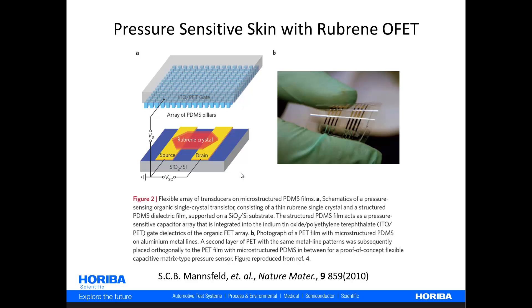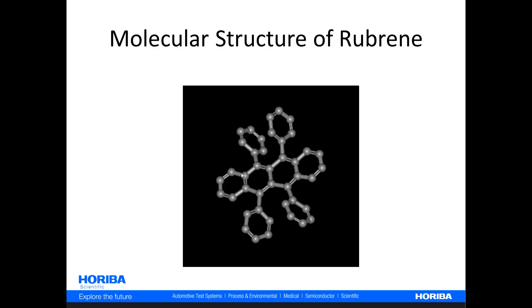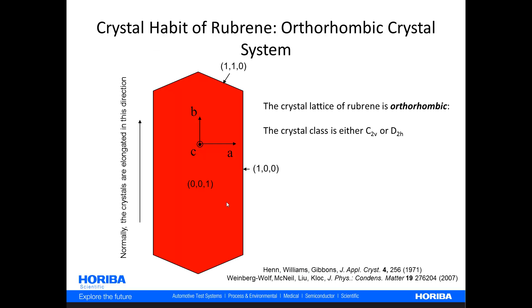This is where the polarization and orientation sensitivity of Raman spectroscopy comes into play. What is the structure of rubrene? It's essentially a compound of fused and bonded phenyl groups. At room temperature it assumes the solid-state and generally the crystalline solid-state. The most general forms are in the orthorhombic crystal system, assuming the crystal class of either C2V or D2H. Generally, the rubrene you'll encounter out of the bottle is fabricated as D2H crystal class, so that's what we'll deal with here.